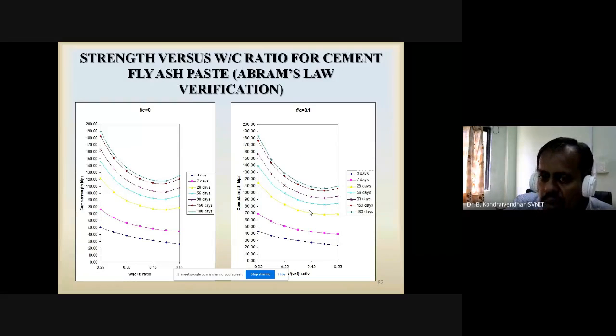Then again, to determine the constant of proportionality K, we have taken a number of experimental data and we have plotted the experimental compressive strength data versus C plus F into alpha into 1 minus P divided by square root of r0.5. That's how we got the K value also. Then by using this value, we can also predict the compressive strength of the cement fly ash paste. Then we also checked the Abrams' law.